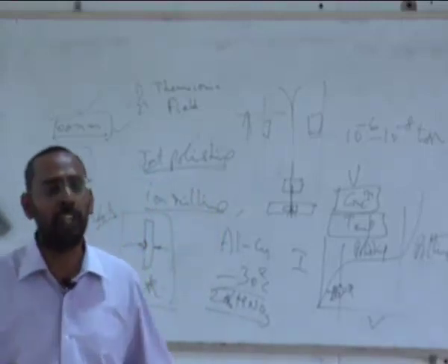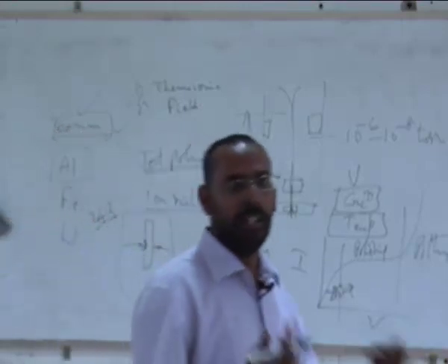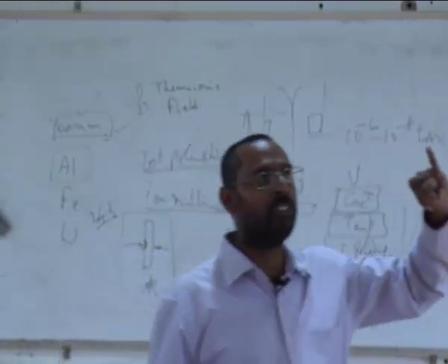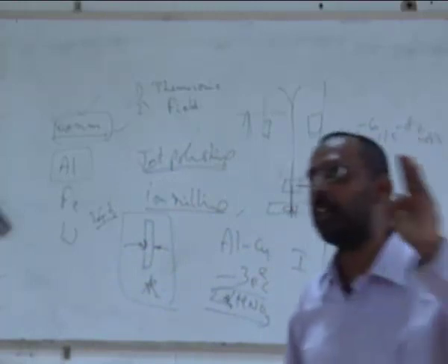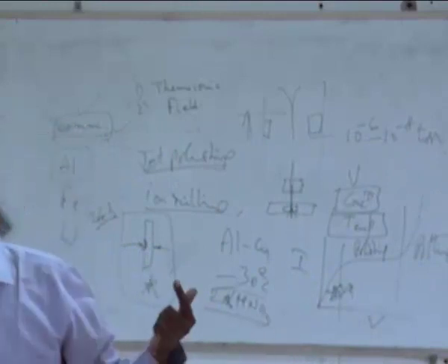Instead of 20, if I use 30 or 40, obviously I am increasing the acid concentration. So the dissolution is faster, and that will influence the whole process. So you need to identify the best solution concentration, you need to identify the best temperature, you need to identify the best voltage conditions. All these three are crucial if you are doing jet polishing.